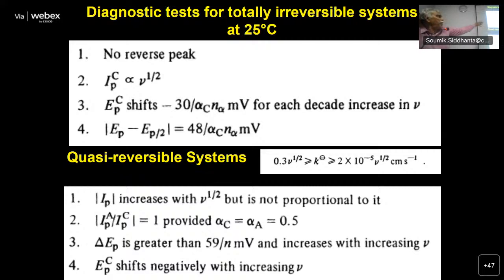EPC shifts 30 by alpha C into N alpha. What is alpha C? Alpha C is called the cathodic transfer coefficient. N alpha is the number of electrons. But the problem now is, if you have more than one step, what is the rate determining step? How much is N for the rate determining step? That is why N alpha means corresponding to the rate determining step.